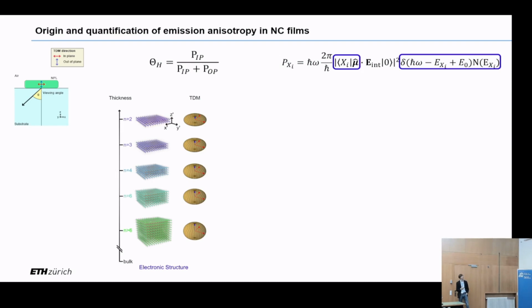and we can have a look at what we can manipulate in this expression. Well, the first thing is the underlying electronic structure, of course, of the nanocrystal. And this is where the biggest difference with respect to molecules lies, because a nanocrystal usually contains a lot more atoms. It has usually high symmetry, which usually leads to a band edge which is highly degenerate. It means that the states which participate in emission are not only one state, but multiple states, each of them independently emitting with their independent transition dipole. And this very easily leads to an isotropic emitter. So this is something that plays in it.